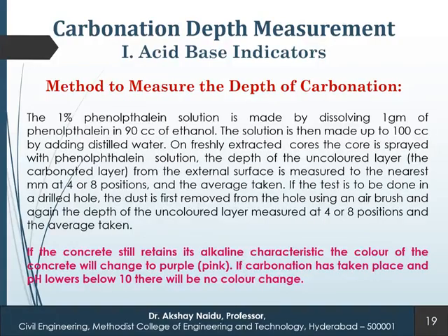How to measure? There are acid-base indicators to measure carbonation depth. How to do so? The easiest method is to take a concrete core cut in the depth of the concrete structure. The core is extracted. On the concrete core, a phenolphthalein solution is sprayed.